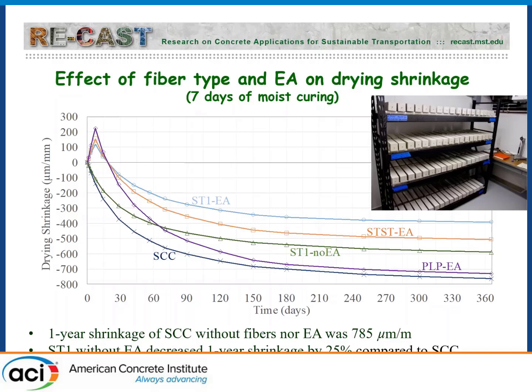I also failed to mention that all of these mixtures have 4% type G expansive agent. This is calcium oxide based; it reacts with water and forms calcium hydroxide and gives you expansion at very early age. So this is the drying shrinkage of specimens that are moist cured for 7 days. And you can see here that for 7 days you have expansion because of the hydration of the calcium hydroxide. And then after that you put them at 50% humidity, and you start having some shrinkage. So this is shrinkage compensation.